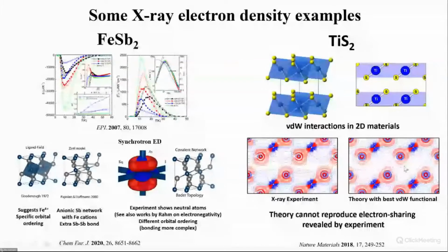We tried also to model this with DFT. We tried all the van der Waals functionals, and you can see none of them can really reproduce the covalency or electron sharing we see by the X-ray experiment. So here is an example where measuring the actual data also gives some good feedback to theory to try to optimize the theory. And currently, it's not really possible to get it correct.